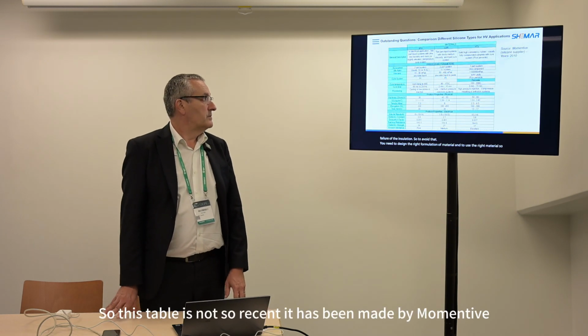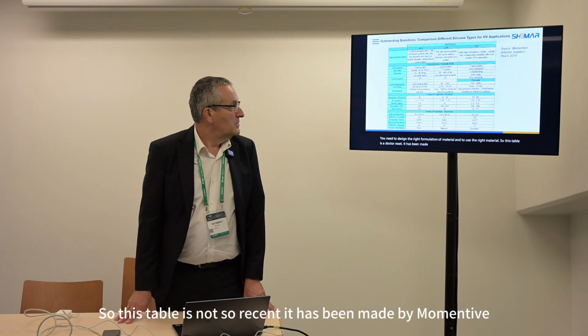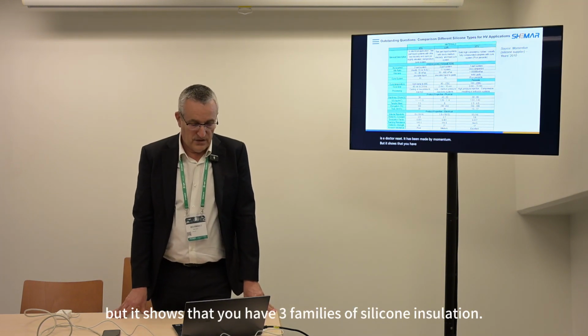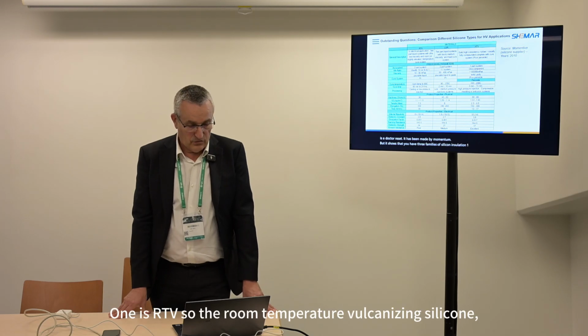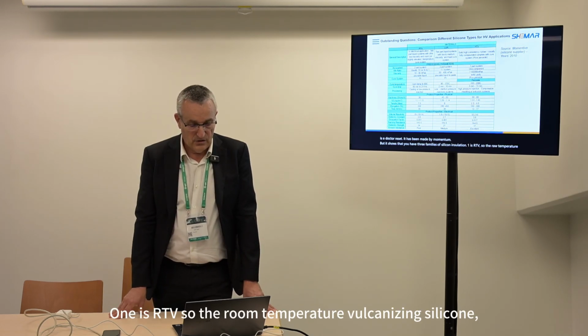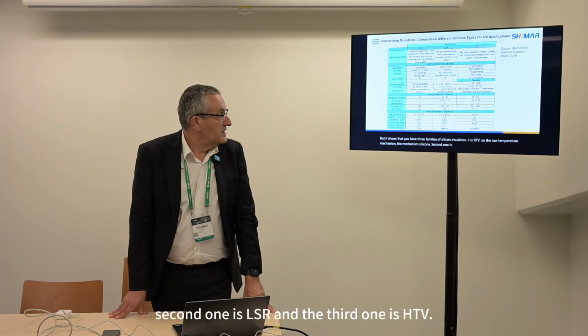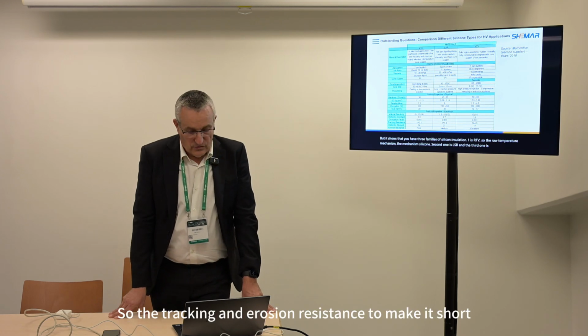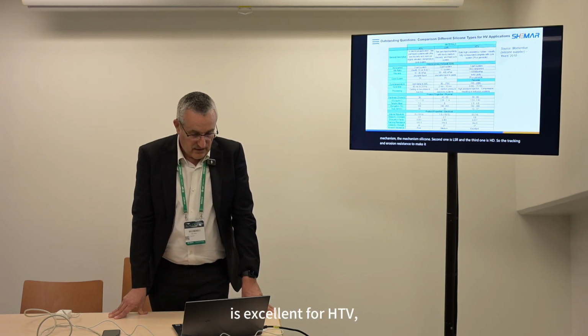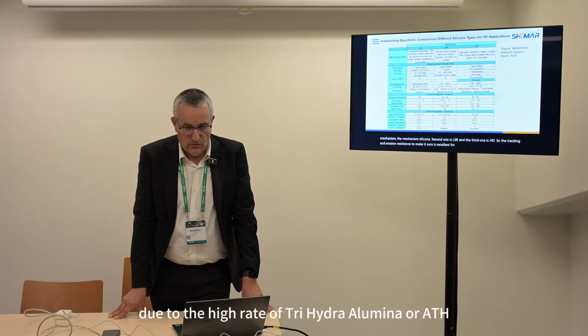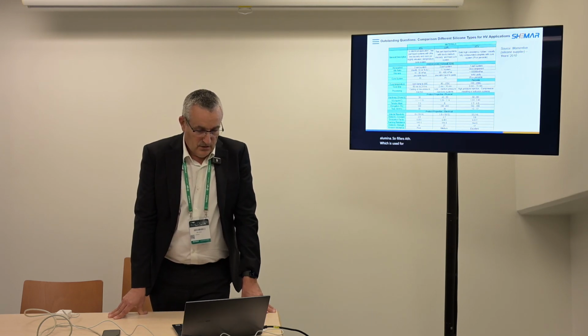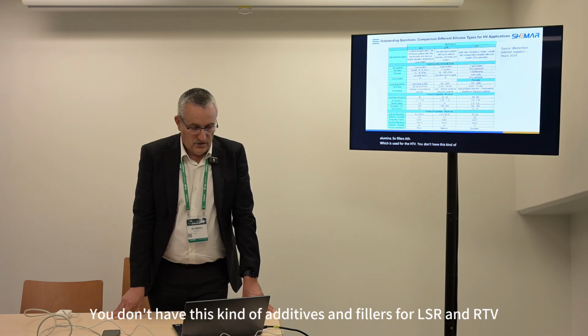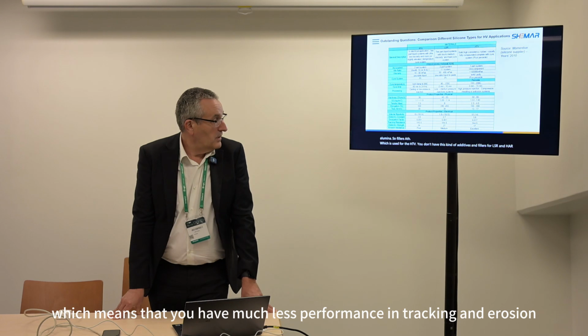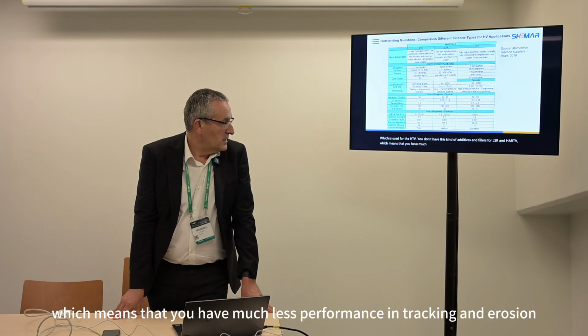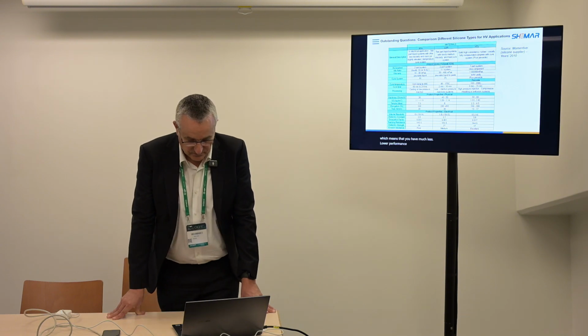So this table is not so recent. It has been made by Momentive, but it shows that you have three families of silicone insulation. One is RTV, so the room temperature vulcanizing silicone. The second one is LSR, and the third one is HTV. So the tracking and erosion resistance, to make it short, is excellent for HTV due to the high rate of alumina trihydrate fillers, ATH, which is used for the HTV. You don't have this kind of additives and fillers for LSR and RTV, which means that you have much lower performance in tracking and erosion.